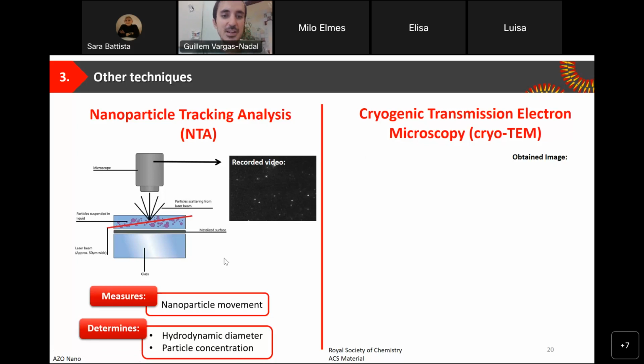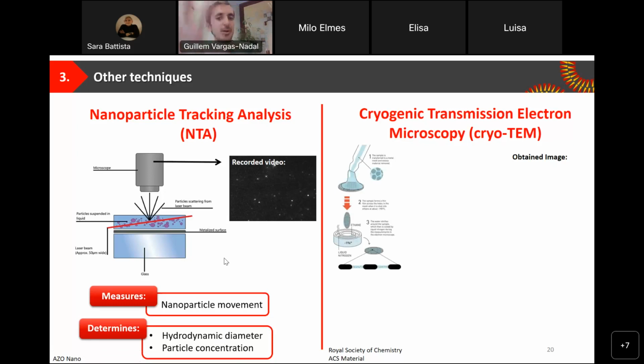Also, this is the hydrodynamic diameter, which is not the real or geometric diameter. Now I move to the other technique, cryo-TEM. In this case, we put the solution over a grid which has some holes. We put the solution, and then quickly we submerge this grid with our solution in liquid ethane, which is surrounded by liquid nitrogen. In this case, we vitrify the suspension. The water is vitrified, it is amorphous when frozen. So this is not crystalline. This is important in order to then visualize the nanoparticles.